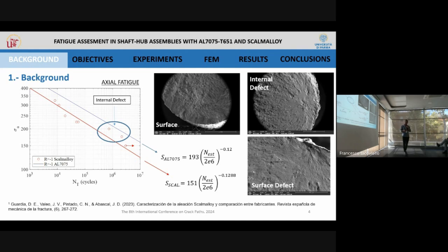It is important to note that for this work, I have fit the S-N curve only taking into account the surface initiation type, avoiding the internal defects, in order to be more accurate in our range of interest.